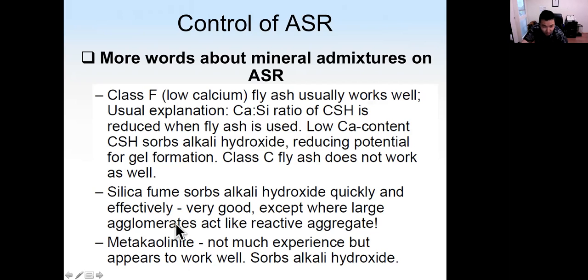Okay. Silica fume can absorb alkali hydroxide quickly, so that is also effective. But pay attention to silica fume. We know silica fume is very, very fine particles. Sometimes the fine silica particles will stick together and cause a very big chunk. And we know silica fume, the chemical composition for that is reactive silica. So if silica fume is stuck together, that will cause a lot of ASR. Okay, so be very careful about that. So make sure silica fume is fully dispersed.